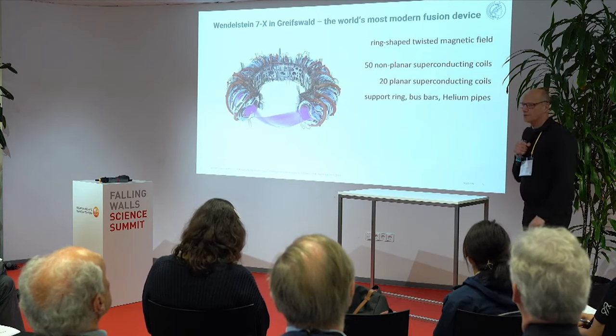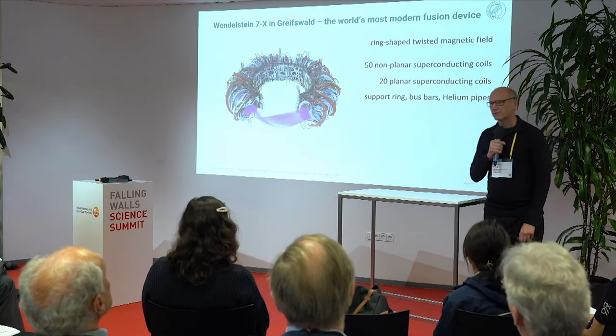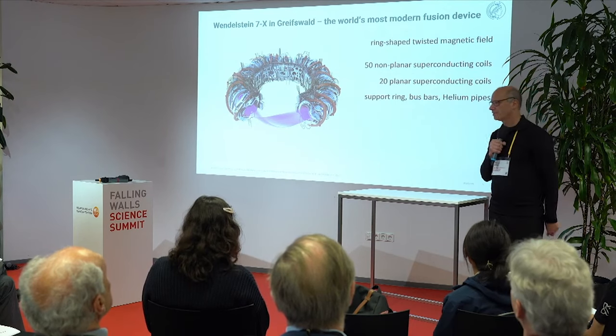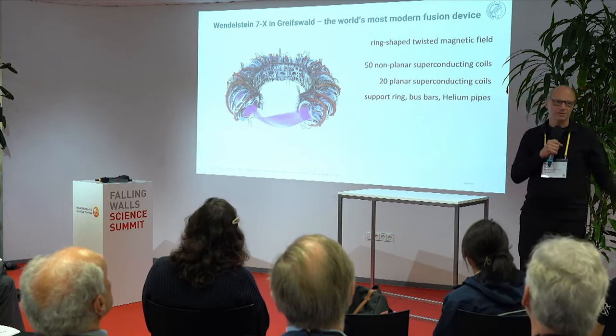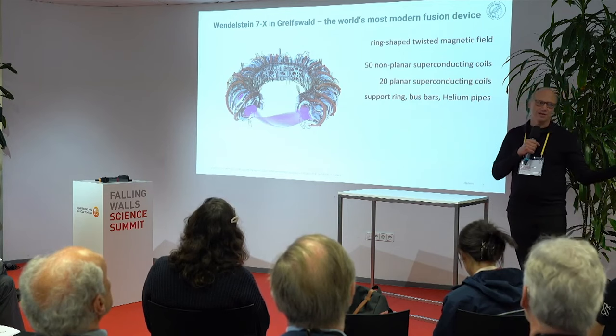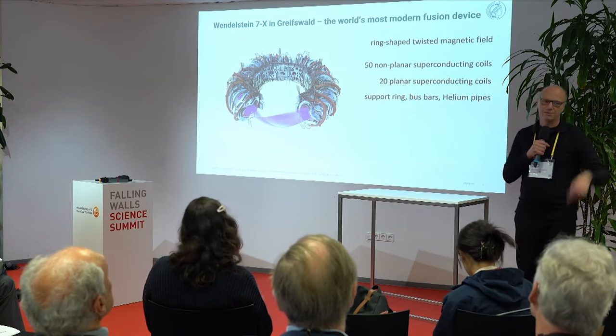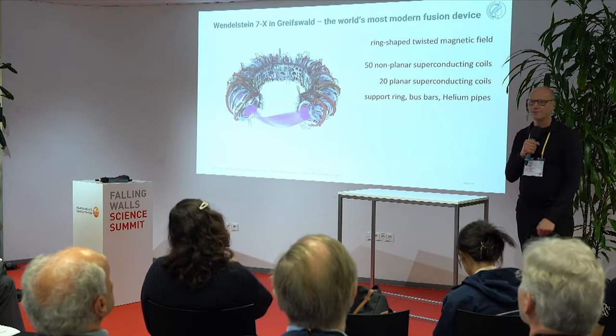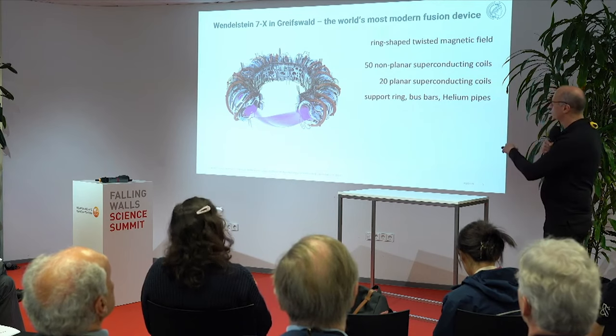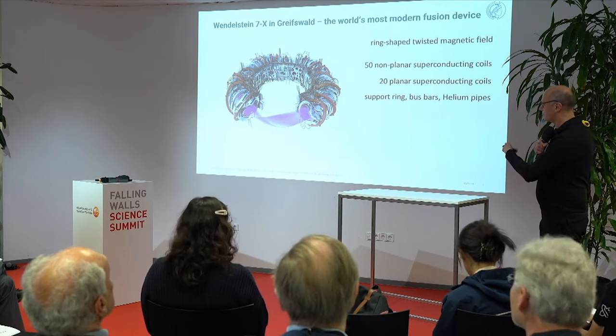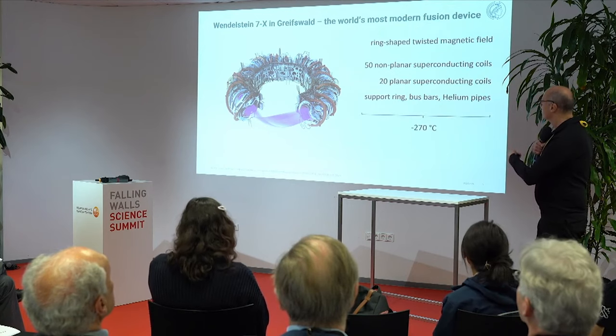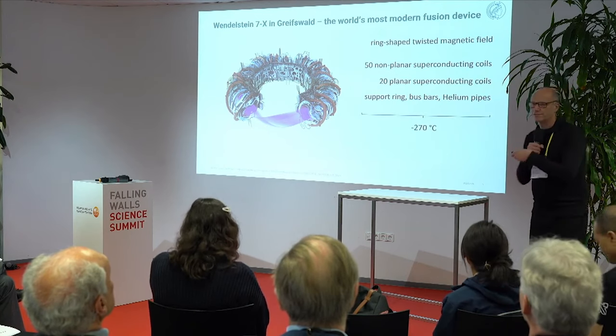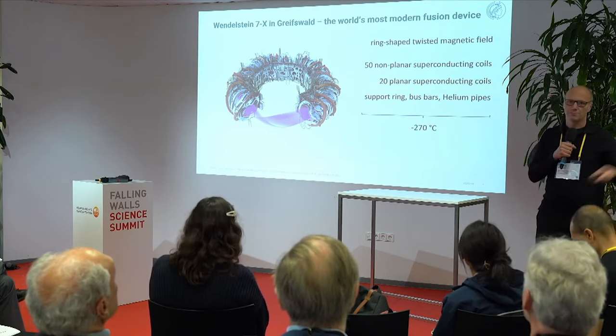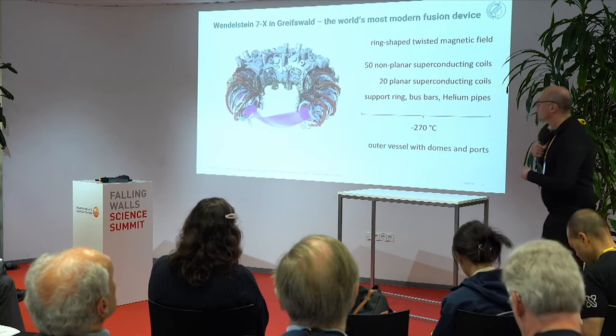Then everything must be bolted to a massive central ring. These coils have a dead weight of 6 tons, 3 meter diameter. The magnetic forces are up to 150 megapascals, so something like 100 tons, 150 tons. And so this all must be supported, they must be wired, they must be supplied with liquid helium, and everything must be cooled down to minus 270 degrees centigrade because it's superconductivity. And so we also need a cryostat.